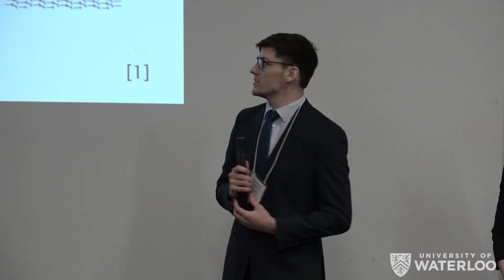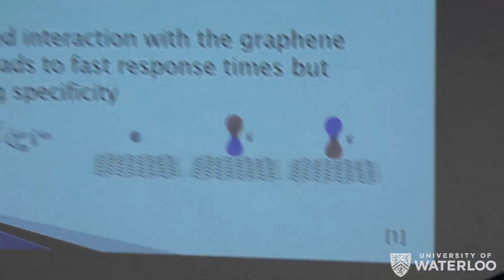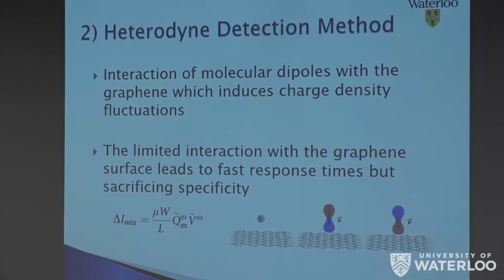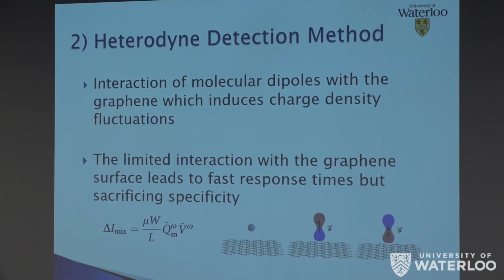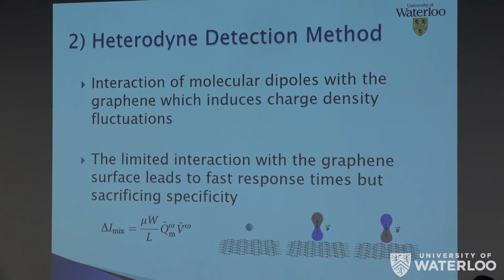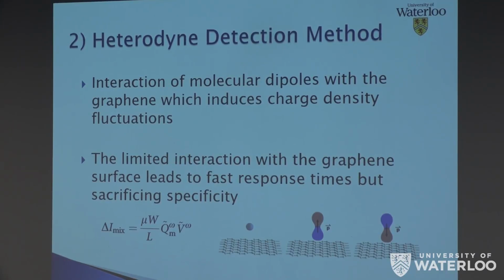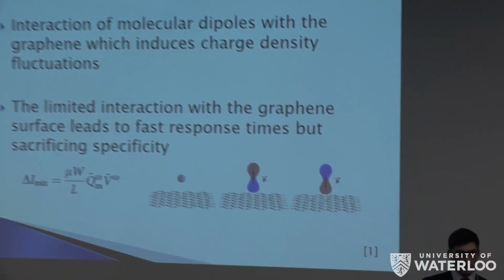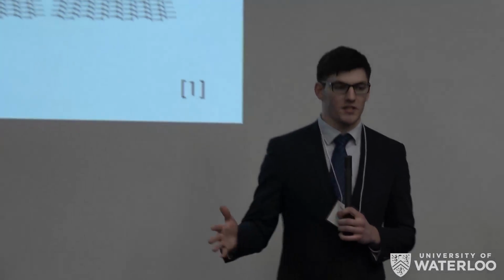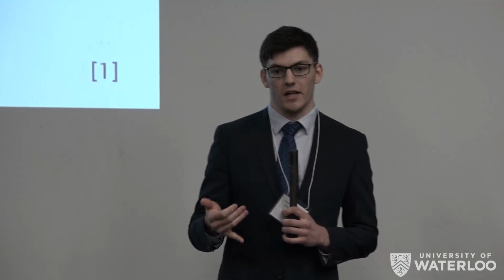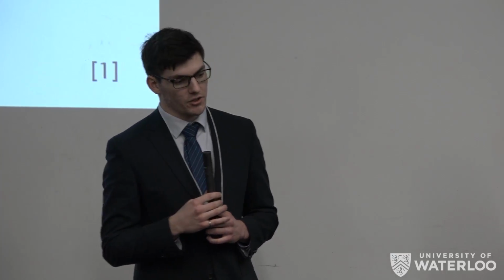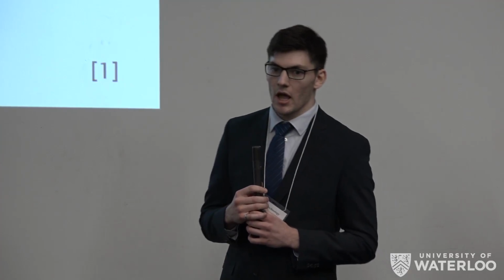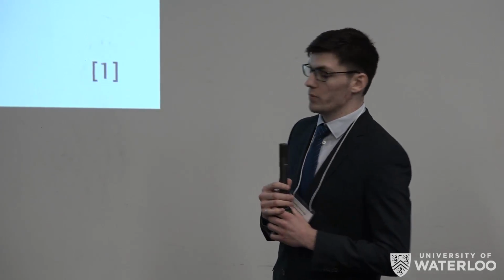The second detection method is dubbed the heterodyne detection method. So what this actually does is it uses an intrinsic piece of graphene rather than functionalized, and it sends in an AC bias that will interact with the polarity of specific molecules. So if you can imagine, if you're running an AC bias across it and the electron cloud is flipping back and forth, this flipping of the electron cloud will induce a polarity shift in polar molecules that approach the surface of the graphene. So as the polarity switches on these molecules near the surface, it actually induces a change in the charge density in the graphene. You can measure this change in the charge density and a change in the output current.